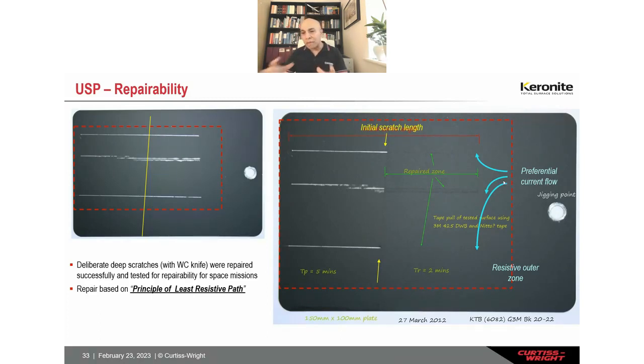So what is happening here is what I call the preferential current flow. So all you need is to repair these components, high-value components, rather than stripping off the entire component. You coat locally where the damage has occurred, and it works on the principle of least resistive path.